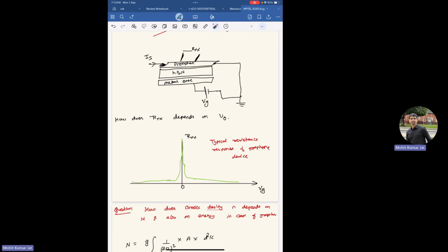The reason is very simple. Your density of states is zero there. Your carriers are essentially not there. Ideally, the resistance should be infinite, but that's not the case because impurities and scatterers are there, which allow conduction through hoppings, basically as in Mott insulators. If you understand the Efros-Shklovskii picture, those hoppings do the conduction, and the conduction happens only through those. That's why the resistance is very high.